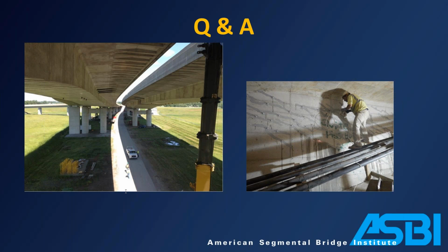These strands are 270,000 PSI, and we're stretching those about 3 feet. That's how much force we're putting in. We're taking that tendon with that jack, and it's like a huge steel rubber band, tightening that concrete back up and closing those cracks. It's not as simple as that, but that was the gist of it: to reinforce those shear zones and those anchorage points and recompress the bridge essentially.